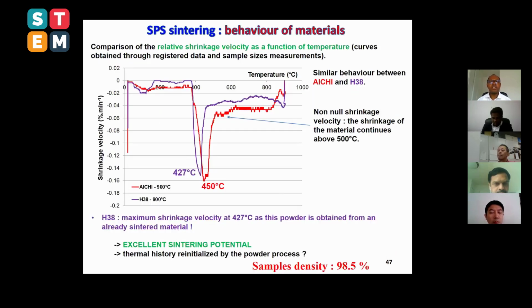Then how about the shrinkage? The SPS gives us here the first answer. This is the Aichi, the red curve is the commercial powder, and the pink one is our, let's just say, the recycling powder. What you can learn here is that the shrinkage is quite similar, and this can sinter easily. This shows us some excellent sinterability of this powder. And the sample we obtained was quite dense, around 98.5%.